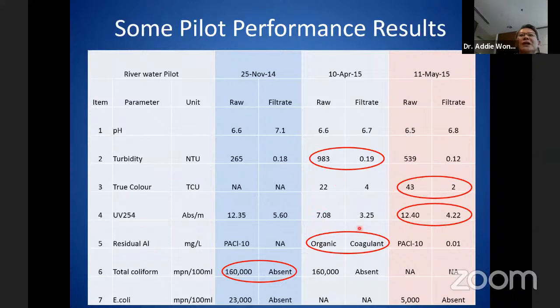Here we show UV254 absorbance, which is like a TOC. It's a simple test using a UV-visible spectrophotometer, so that's how we monitor. Doing TOC takes a very long time and is very expensive. So we use the UV254 absorbance meter to check the organic content, or DOC, in the water. You can see the removal is very significant, almost two-thirds removed. Okay.